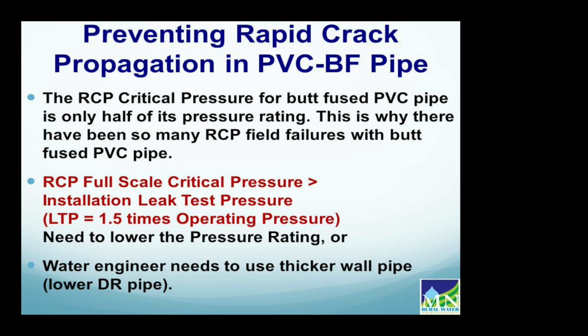The key point is that the full-scale critical pressure needs to be greater than the leak test pressure, which is 1.5 times the operating pressure. If it's not, then we need to lower the pressure rating as a way of preventing RCP. Another way would be, if you need higher pressure than what that calculates to, you need to use a thicker wall pipe or a lower DR number. So if you're using DR25, you might need to use DR18 or DR11 or whatever.